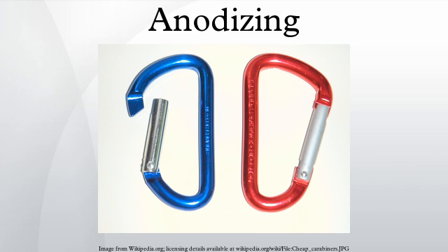In typical commercial aluminium anodization processes, the aluminium oxide is grown down into the surface and out from the surface by equal amounts. So anodizing will increase the part dimensions on each surface by half the oxide thickness. For example, a coating that is 2 μm thick will increase the part dimensions by 1 μm per surface. If the part is anodized on all sides, then all linear dimensions will increase by the oxide thickness. Anodized aluminium surfaces are harder than aluminium but have low to moderate wear resistance, although this can be improved with